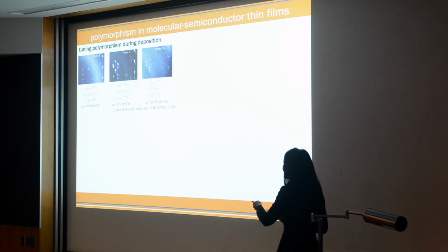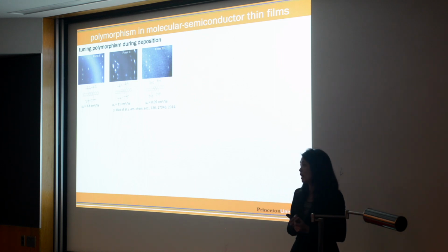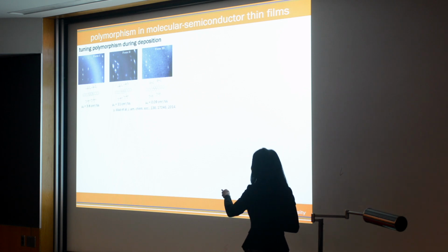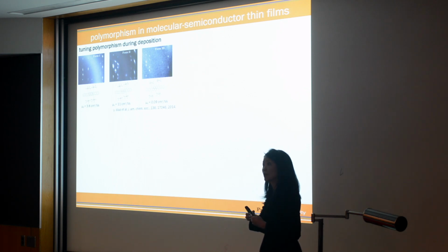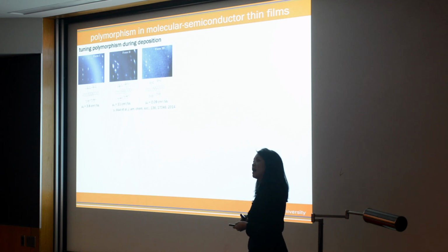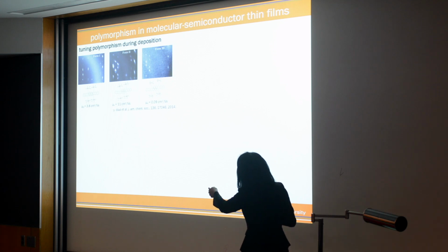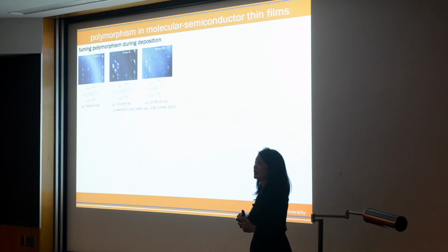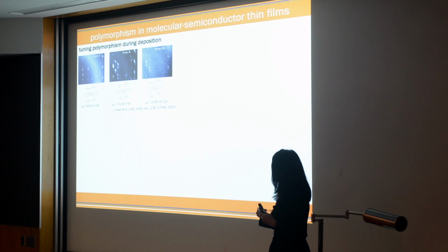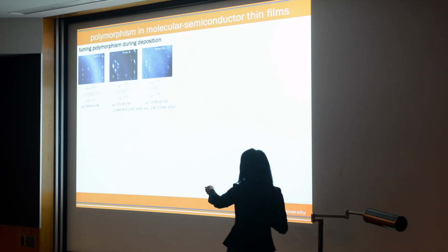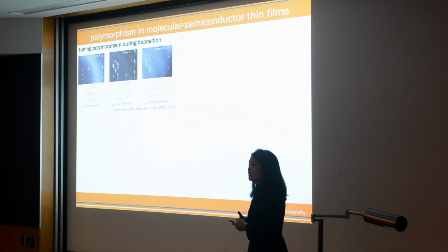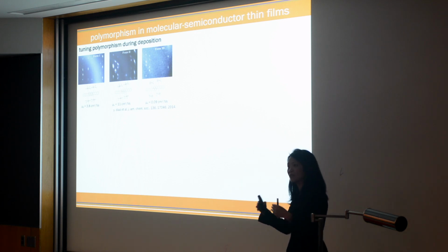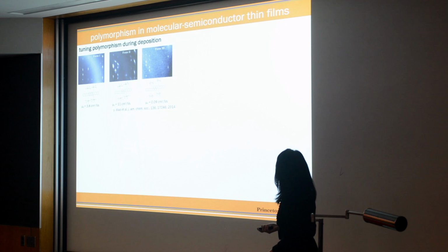So this work is by Ying Diao, who's now at UIUC, and this was her work while she was a postdoc in Zhenan Bao's group. This is with TIPS pentacene. Here, TIPS pentacene adopts the same two-dimensional brickwork packing, but she shears this film as the film is crystallizing. Because of this shearing, you can see subtle differences in the extent of pi orbital overlap in the charge transport direction. And because of this difference, you see, again, differences in the mobility. It's the same class of packing polymorph, but slight differences in the packing motif.